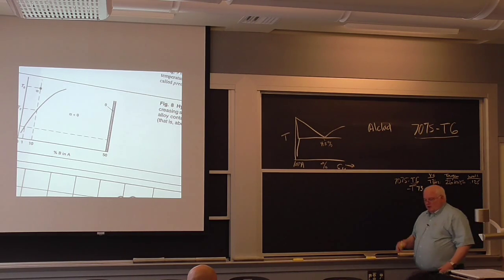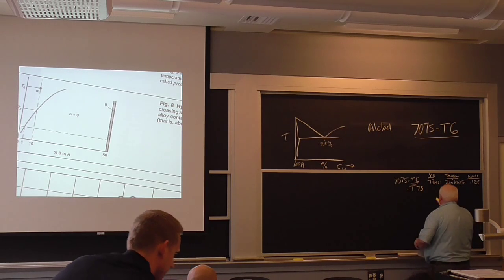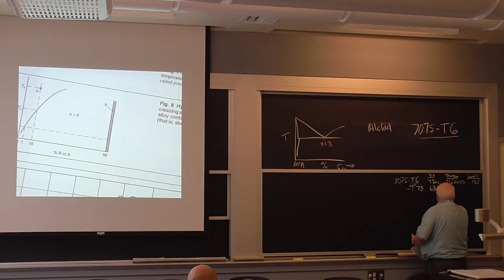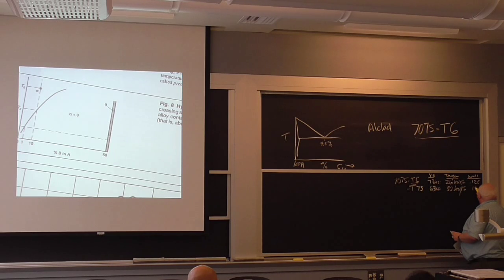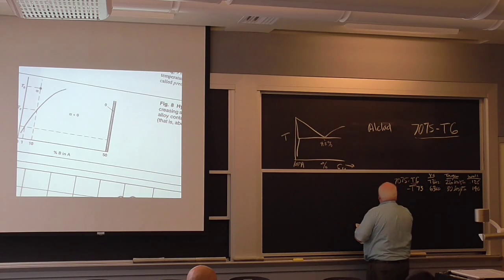And the properties, we go look it up in the handbook, the properties 63 KSI and 30 KSI root inch, that's square root inch. And it turns out, in my calculation, to make everything work out in terms of strength, we had to up the wall size to be able to hold 7,500 PSI operating pressure. So it turns out, I ought to write this out someday. It was operating at 63% of yield, was their design criteria.